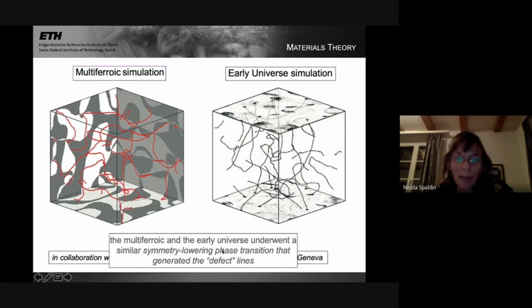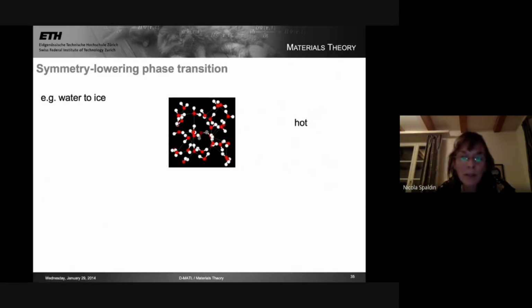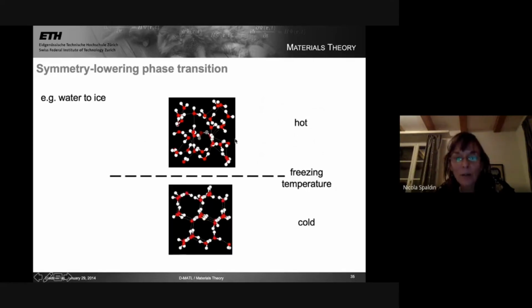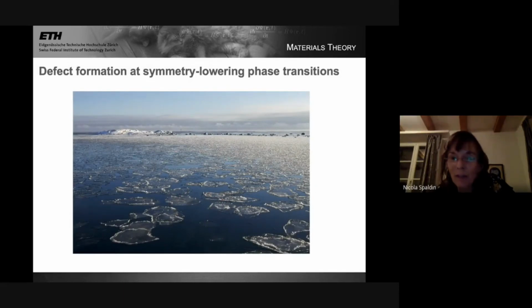So the multiferroic and the early universe both underwent a similar, what's called a symmetry lowering phase transition that generated these defect lines. A symmetry lowering phase transition would be, for example, water freezing and going to ice. It goes from being high symmetry, where every direction looks the same in the water, to low symmetry in the ice, where it looks different when you look upwards or to the right. Associated with symmetry lowering phase transitions is the formation of defects.